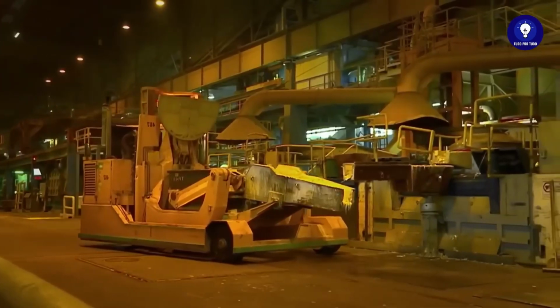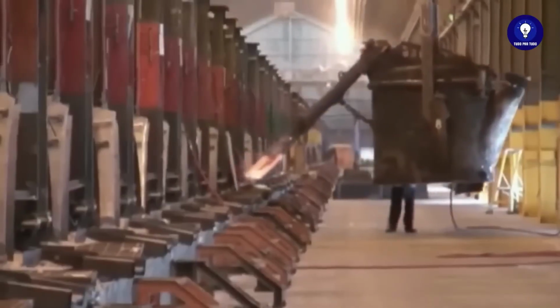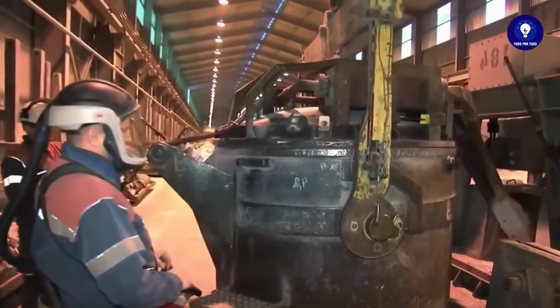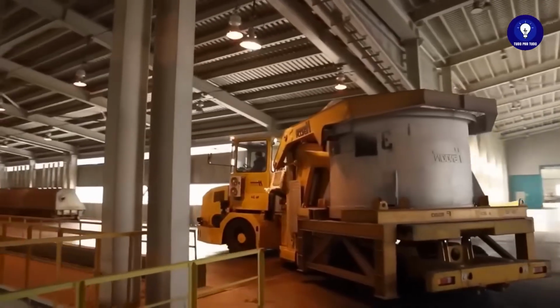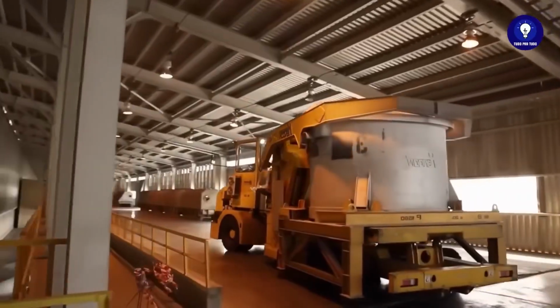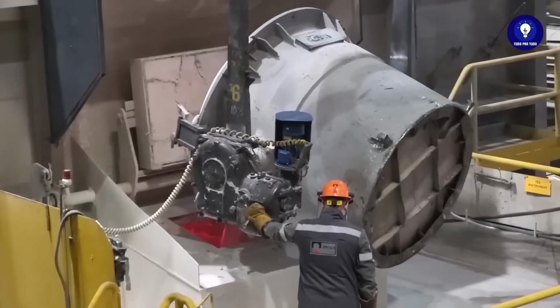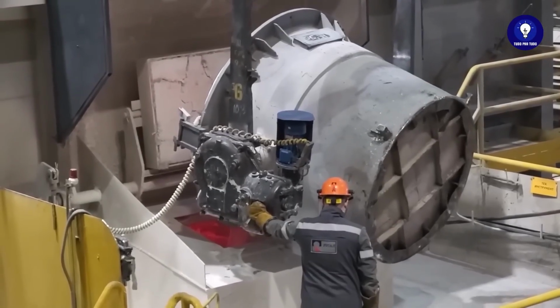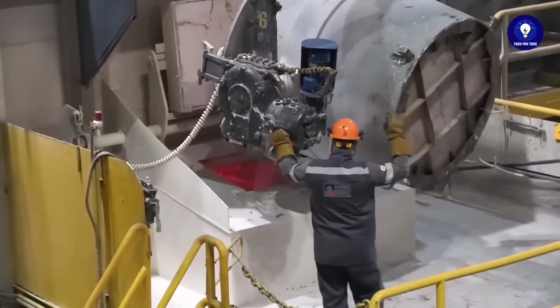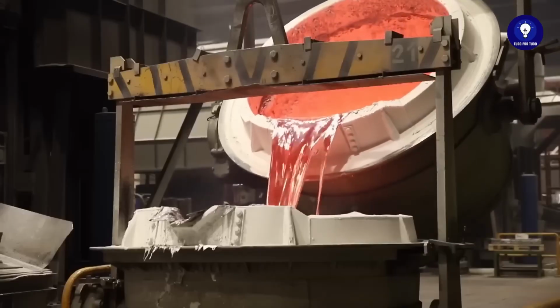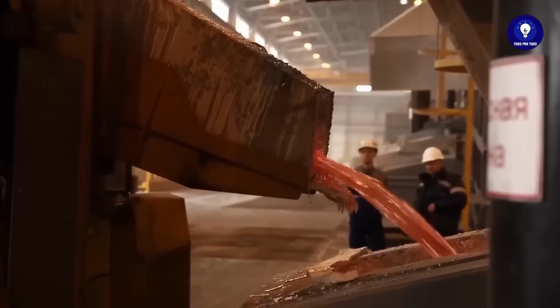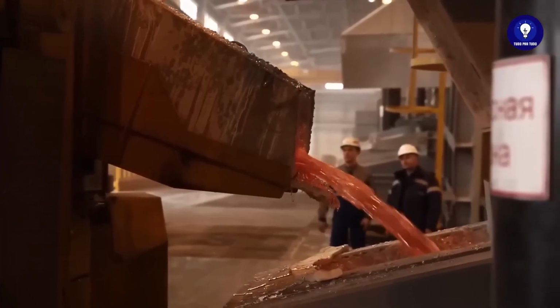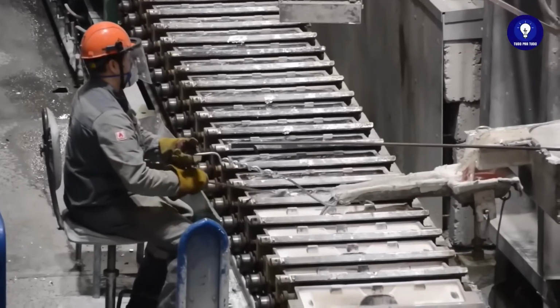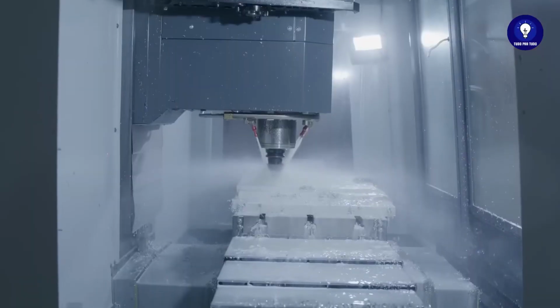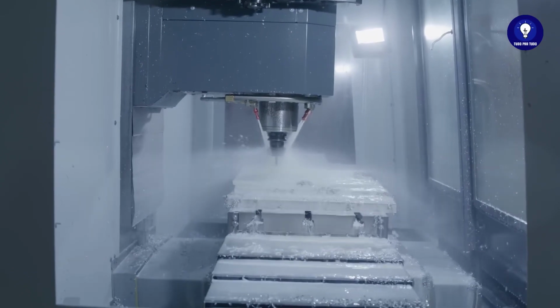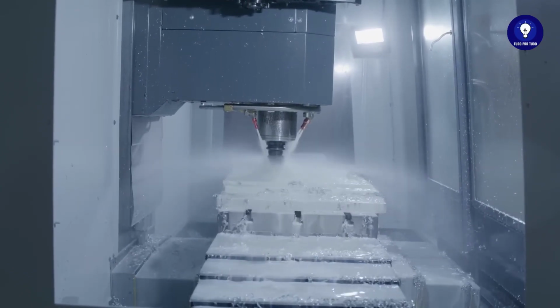Once extracted, the liquid aluminum is transferred to a transport crucible, a thermally insulated container designed to maintain the metal's temperature and prevent its premature solidification. In the refining furnaces, the aluminum is reheated to eliminate remaining impurities through processes such as filtration, which remove unwanted elements like hydrogen and oxides. Next, the pure aluminum is poured into molds to form ingots and subjected to a controlled cooling process, ensuring that it solidifies without structural defects.